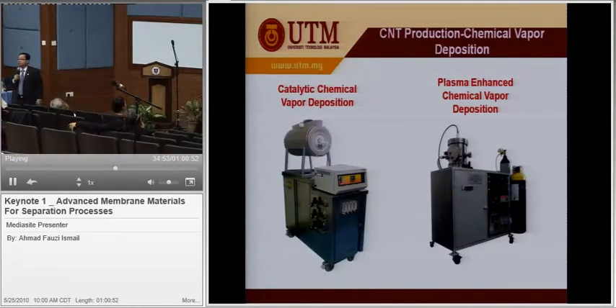This is some of the machines that we design and we fabricate in the lab. And we produce our carbon nanotube using this machine. We have 2, one called catalytic chemical vapor deposition, a very simple one, just a quartz tube with a furnace. We grow the carbon in the tube. From that we can produce, but it's a bit impure. So in order to produce purer material, we designed and fabricated what we call a plasma enhanced chemical vapor deposition system, purer products. The machine is in the lab.